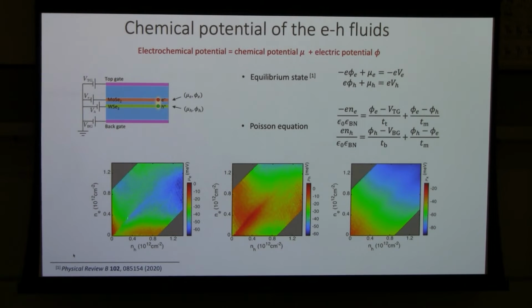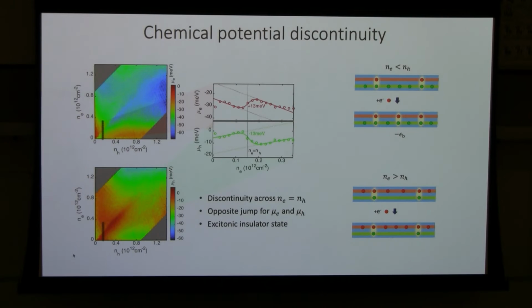So in this mapping, what you can see is that in the diagonal direction, there's a very clear feature in the chemical potential for electrons and the chemical potential for holes, but not so much for the excitons. We can understand this feature a little bit better by doing a line cut. Here I reproduce the chemical potential and look at the chemical potential change as a function of the electron density when the hole density is fixed at about 0.2 times 10 to the 12 per centimeter squared.